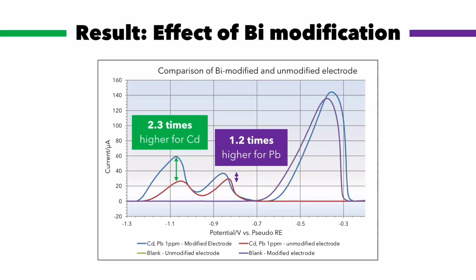Furthermore, modified electrode and bare electrode were compared, matching with the result of blank condition. And for sure, the current signals from the bismuth modified electrode were remarkably enhanced. The increase in stripping currents could be observed due to the bismuth providing increased surface and facilitating a better deposition due to the formation of amalgam with lead and cadmium.